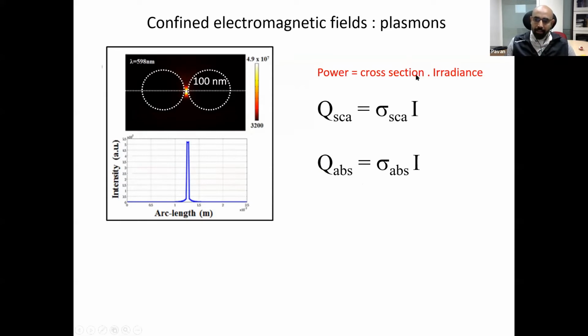Now, the interesting aspect is that this cross section is very much a property of the material you are taking into consideration. And it happens that at optical frequencies, the cross section of the scattering and also the absorption of, let's say, a gold nanoparticle, or any other kind of noble metal nanoparticle, is very high. This is one of the reasons why we extensively use gold nanoparticles and also silver and other kinds of particles, because it provides enhanced interactions, because the solid state aspect of electron density comes into the picture, which further facilitates something called the plasmon frequency and also the surface plasmon polaritons, which is a kind of collective oscillation of light and the electron charge densities in the metal.